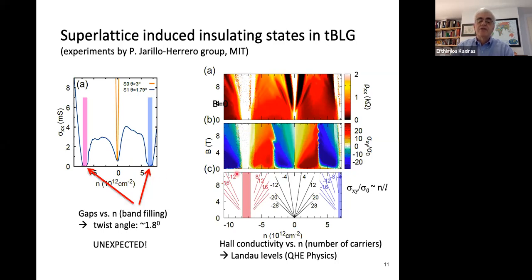And here's another set of measurements, also from the same experiment, showing the behavior of states when you introduce an external magnetic field. And again, as a function of doping, you observe this behavior of the off-diagonal part of the conductivity. And these lines are an interpretation of the conductivity, which is proportional to the number of carriers divided by the Landau level index. And you see that in these lines, the Landau level index jumps by 8 for this range of values of doping. For another range of values of doping, the index jumps by 4. And again, this is Hall conductivity, quantum Hall effect physics, and Landau levels observed, but with their own peculiar behavior.